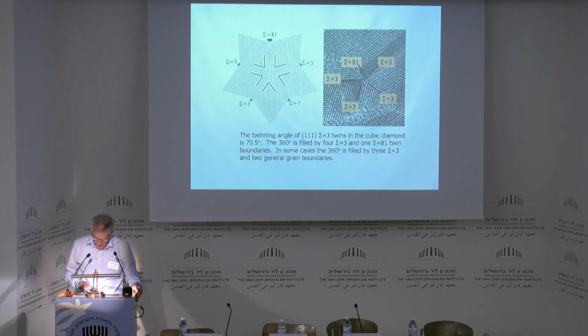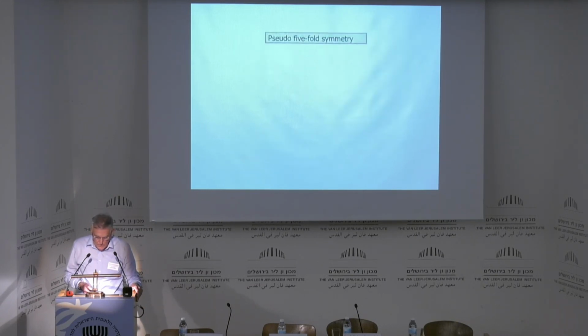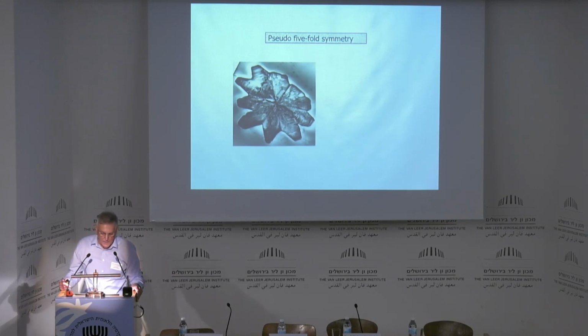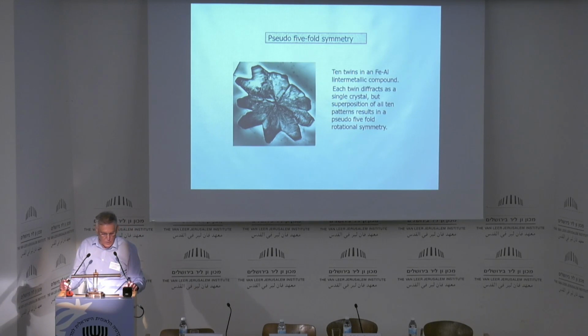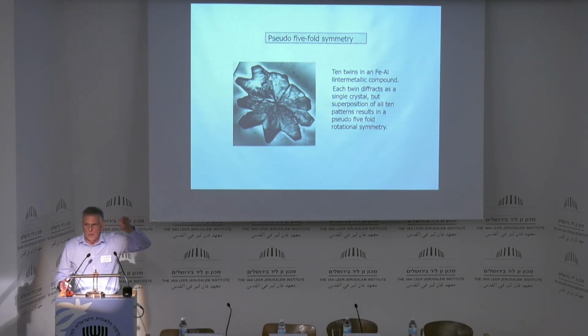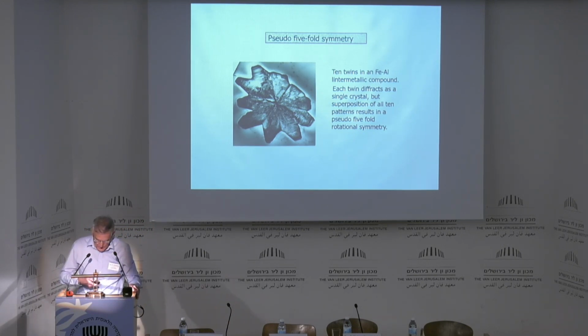Now, okay, you've seen this. Here is another example. This structure is also a twin structure. It exists in the aluminum iron system, very common. And what you see here, you can see in an electron microscope. These are large crystals, really large crystals. An optical microscope is good enough to study them. And what you have here are 10 twins. You can count the number of petals on this flower-like crystal. And these are all twins.